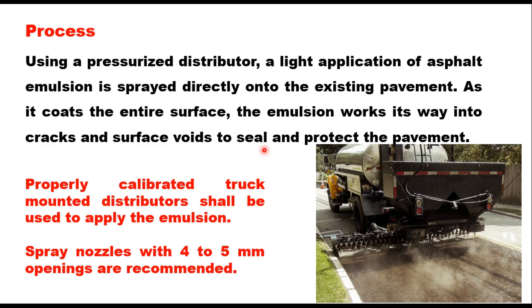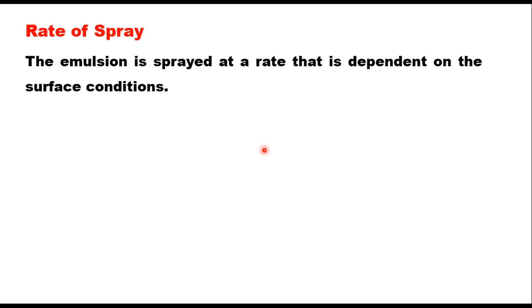Spray nozzles with four to five millimeter openings are recommended in IRC SP100. The emulsion can be heated to a maximum of 50 degrees centigrade, although generally emulsion is sprayed at ambient temperature. The rate of spray is dependent on the surface condition.